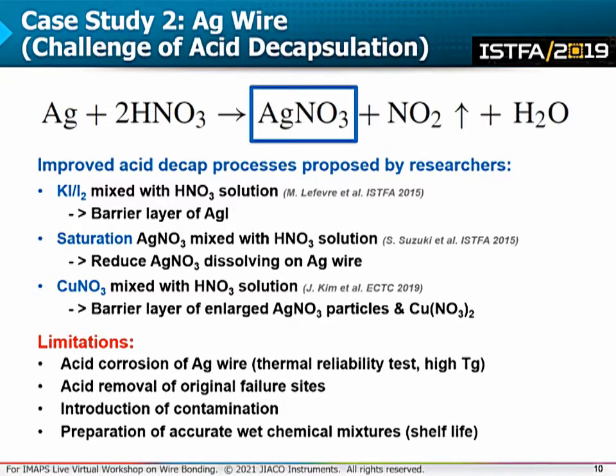One of them is just the addition of diluted iodine or iodide solution, and the other one is based on adding copper nitrate to fuming nitric acid. By that, a barrier layer of cupric nitrate and silver nitrate particles will be formed along the silver wire. One more method is saturation etching, where researchers used silver nitrate to saturate fuming nitric acid, and in that way the damage of the silver wires was also largely avoided. However, this approach requires a specific reserve type of acid system. Even though the proposed methods did bring some improvements, there are still drawbacks and limitations to them.